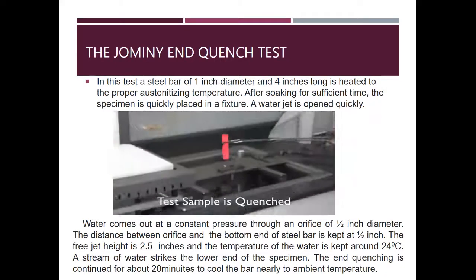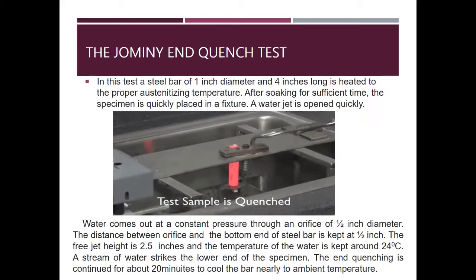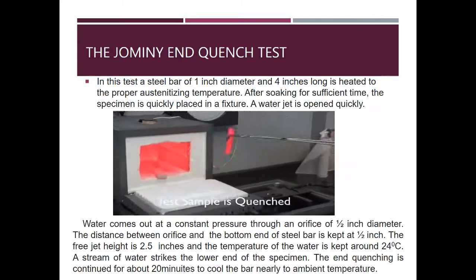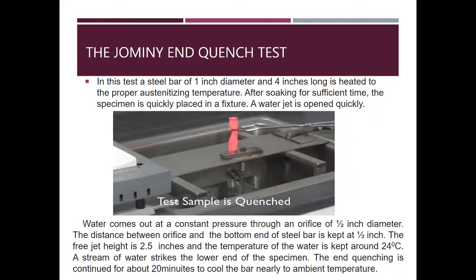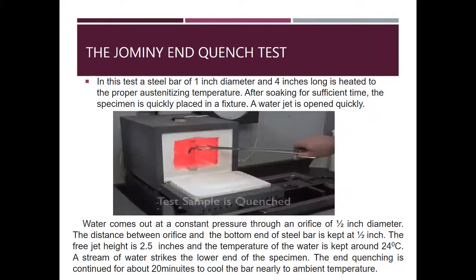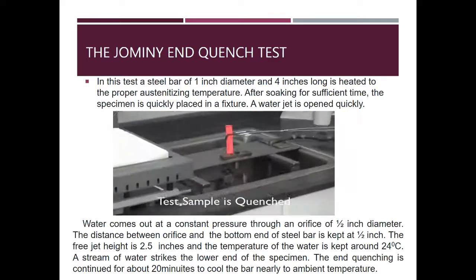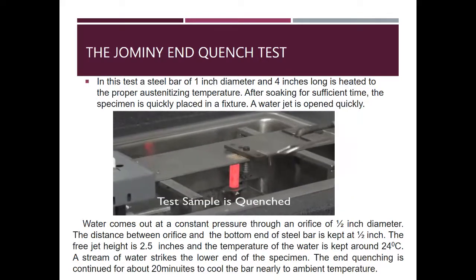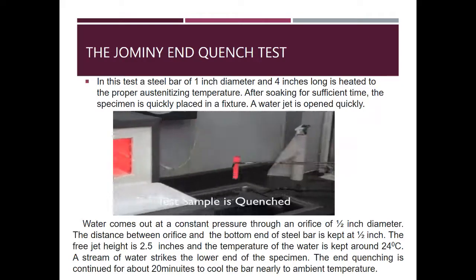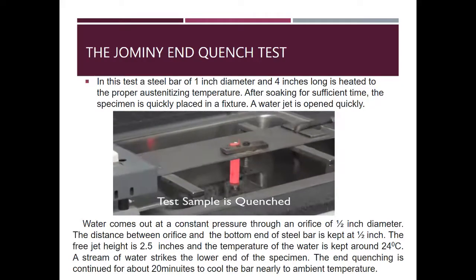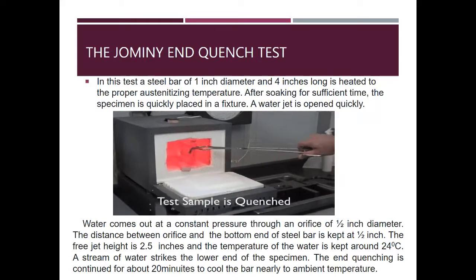In the Jominy end quench test, a steel bar of 1 inch diameter and 4 inches long is heated to the proper austenitizing temperature. After soaking for sufficient time, the specimen is quickly placed in a fixture. A water jet is opened quickly.